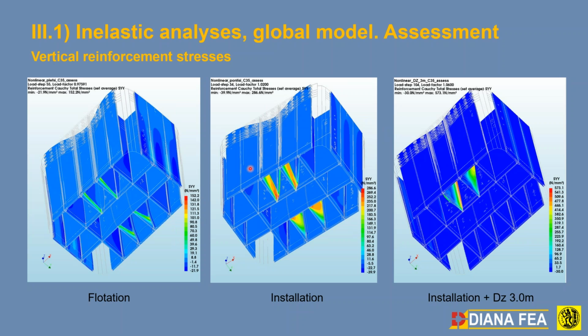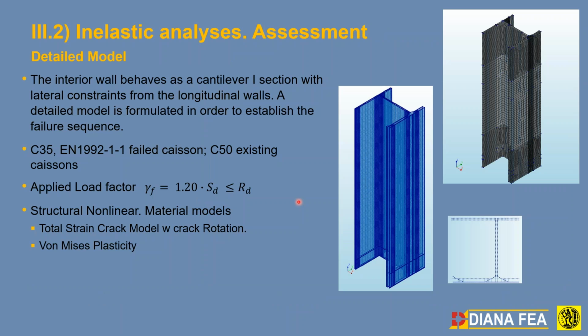Okay, so we decided to look at this particular subassembly more carefully using a more detailed model. Again, we do an assessment in inelastic only now. We did an elastic check just to check the model, but it's no real bother. Now, again, we do same kind of materials, same kind of material grades. This is the typical longitudinal and transverse reinforcement, stirrups included, as embedded rebar now inside the walls, including all these triangular thickness zones, which is part of the design. The full cantilever height. This is the fixity side. This is the fixity with the mirror rollers, because there is a mirror, same compartment at the edge.